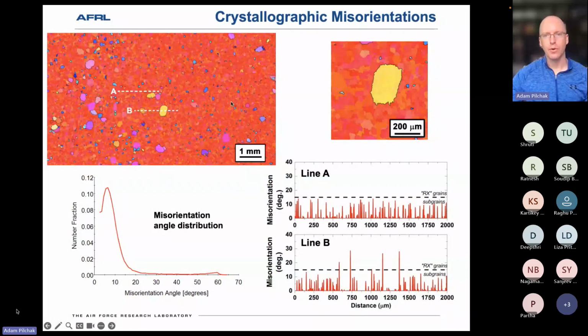If we now just take some line profiles through that, so line A here, I'm just cutting through all of that subgrain matrix. So you see a whole bunch of misorientations that are, say, less than 15 degrees or so. In line B, where I'm cutting through a couple of these recrystallized grains, when I'm in the matrix, I have a lot of these local misorientations. When I get inside of that recrystallized grain, misorientation drops to near zero, indicating that it's relatively recrystallized, strain-free. And the same thing happens when I cut through this larger yellow one over on this side.